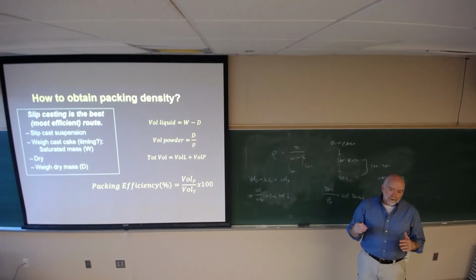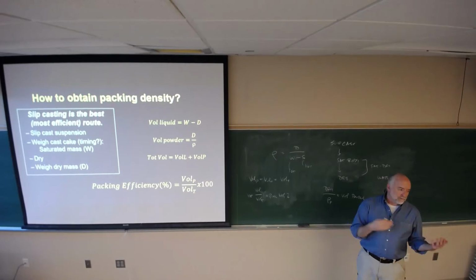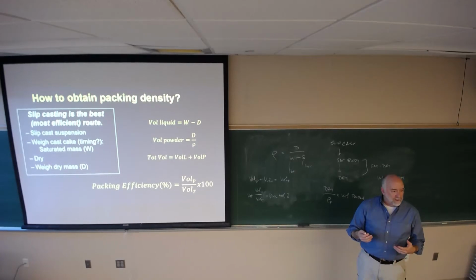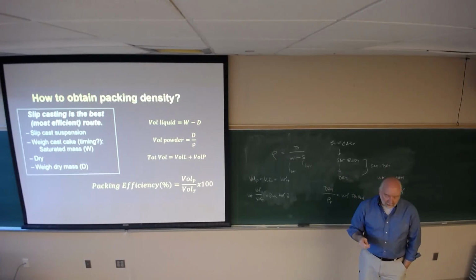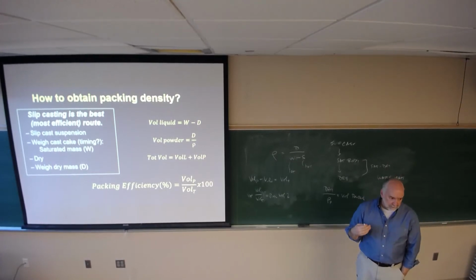So if you do it early, you have liquid slip left on top of the cast. Well, that's overestimating the water content. And if you let it sit there, what happens? Evaporation, you lose water, then you'll underestimate your pore volume. Right? How do you reduce the evaporation of water? How do you know that you're at the saturation point when you're done?